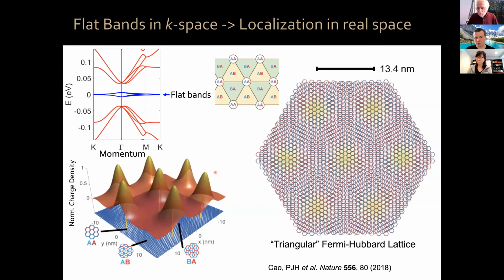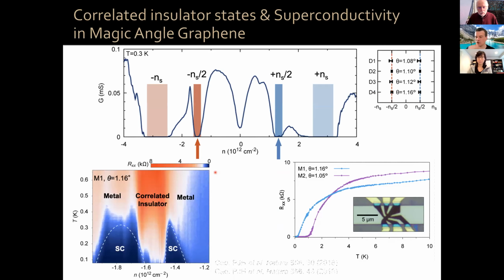Now, what we discovered back in 2018 is that if you put your Fermi level in those flat bands, at certain numbers of electrons per Moiré unit cell or numbers of holes per Moiré unit cell, you get correlated insulating states.